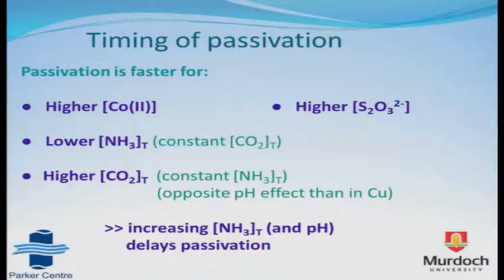And again, the timing of passivation takes place faster for higher cobalt and thiosulfate concentrations, for lower ammonia concentrations, but in this case, increasing the carbonate concentration appears to make passivation take place faster, which is the opposite to what had been observed in the case of copper.